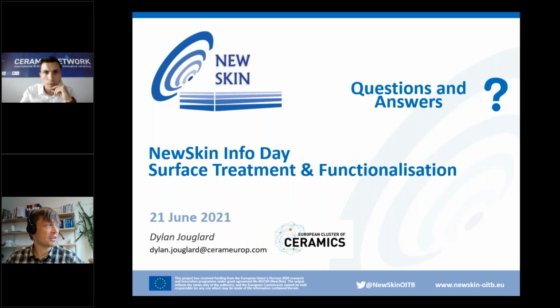And I know that gears are fairly difficult because as far as I know, they are manufactured fairly rough, and then there is some running-in period in which the surface gets smoother. So it's difficult to use such coatings there, I'm afraid. Okay, thanks, I understand. Thank you.